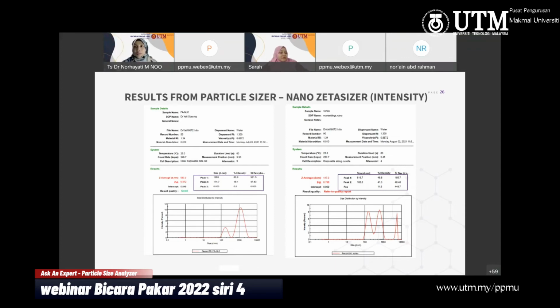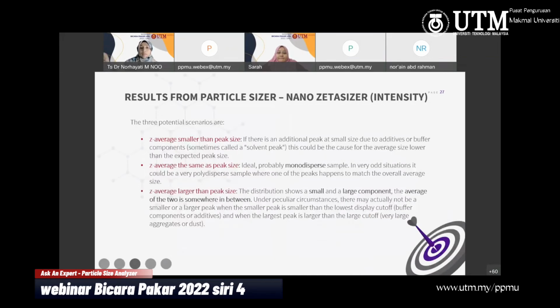But if the result is not good, probably your sample is too large, or too polydispersed. If your sample is fluorescent, they will give you some information in that tab. So you know that maybe your sample is not stable, so you have to improve your surfactants. They will give you some indicator. From that result, you can see the potential scenario. If the Z average is smaller than the peak size, there is an additional peak at small size due to additive, buffer or components. Sometimes when we do dilutions, it might give you a solvent peak, because the average size is lower than the expected peak size.